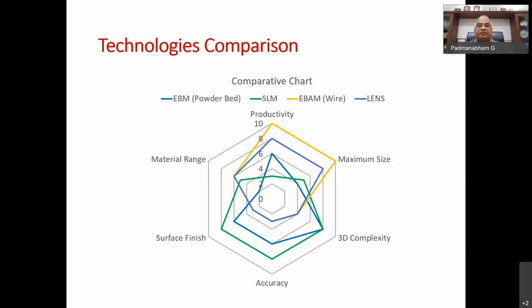When you are looking for, let us say, high surface finish and high accuracy, the green contour, you can see it, that is the SLM method. Because we use very fine powders, we build only a 30 to 40 micron or 50 micron layer using an 80 micron spot. But then today, the SLM machines that are available are not very big. So you have a debit in terms of maximum size.